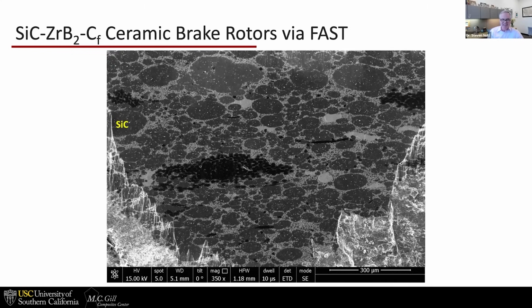This is a work in progress. This is a very low magnification showing the distribution of the phases. The matrix is basically silicon carbide and zirconium diboride. The fibers are carbon fibers. They're chopped in bundles, and all of this is sintered in a matter of minutes. I mean, this is not a really homogeneous distribution of phases. They're the carbon fibers. The big islands are silicon carbide, and in between the islands are predominantly zirconium diboride. Little white flecks that you see there are not surface dirt. That's actually alumina yttria sintering additives.